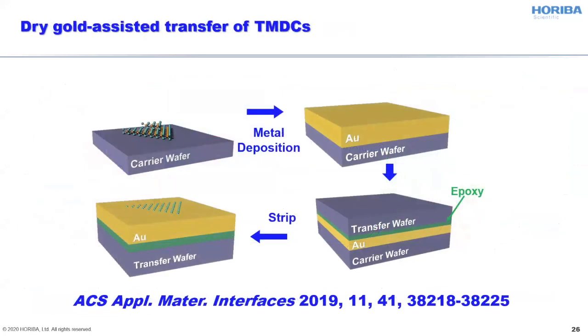So we took the carrier wafer with the crystals, then evaporated gold on top. Then we glued a transfer wafer with a thin layer of epoxy, and then we stripped the crystals from the carrier wafer. And thus we obtained a situation where our crystals were embedded in the gold layer, and that provided us with